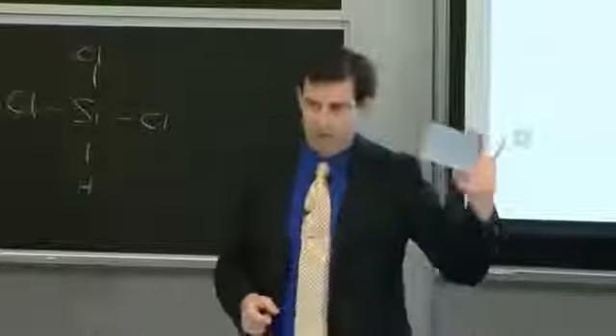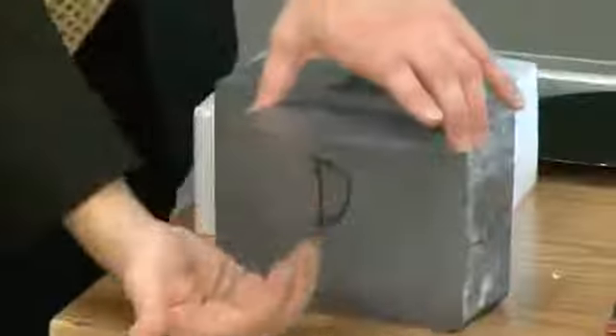So when I pick up a wafer like this, this wafer was chopped from the ingot this way, or to put it into perspective here, this wafer was sliced out like that from this, so that the grain boundaries were running perpendicular to the surfaces. And that way, they don't impede as much with electron transport.